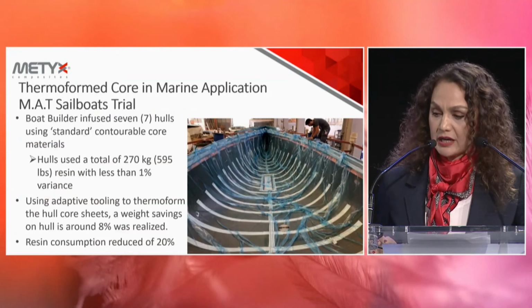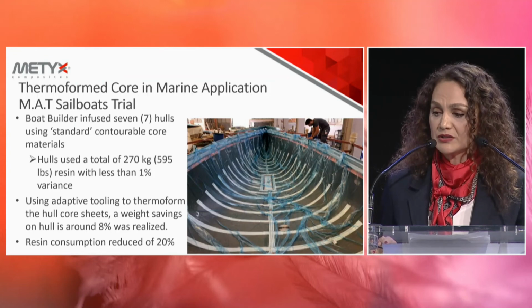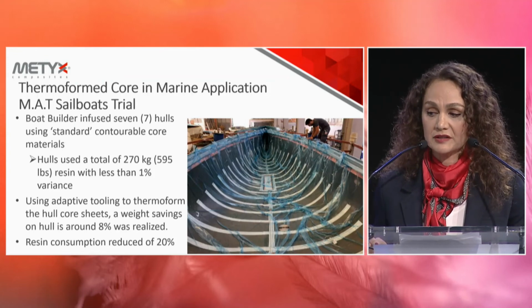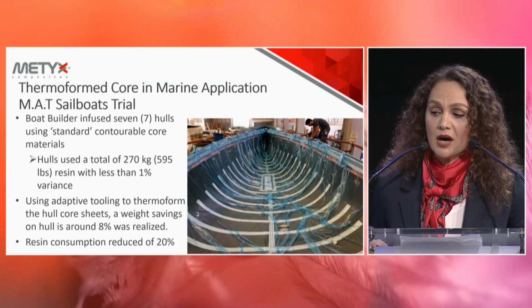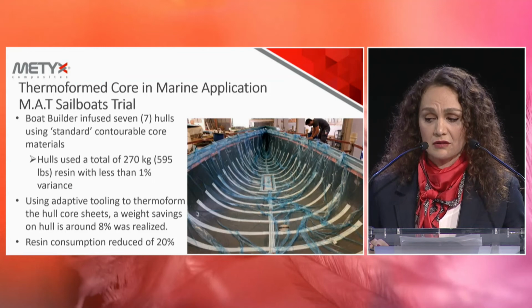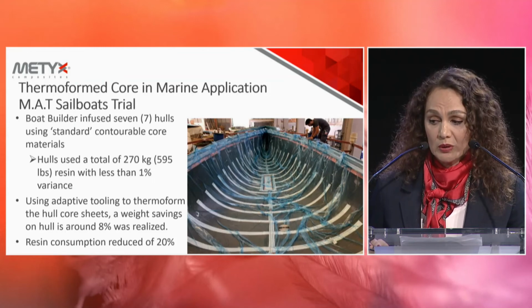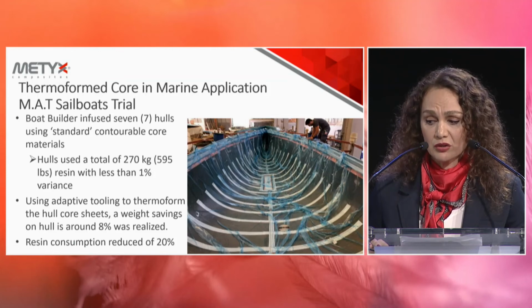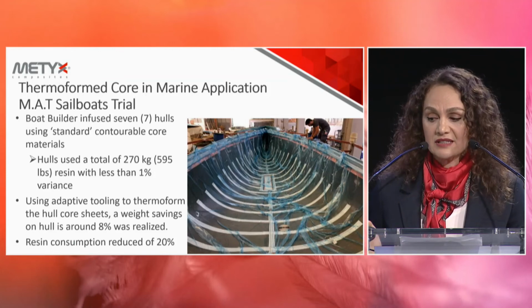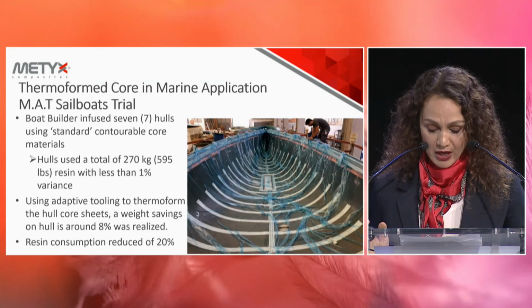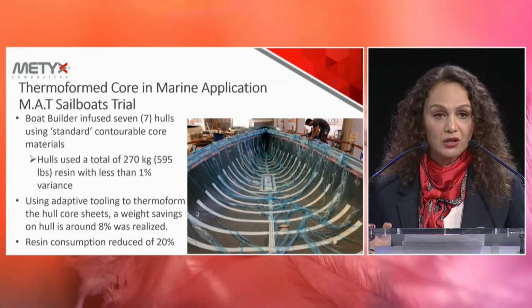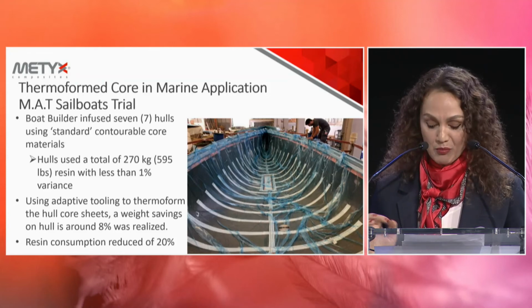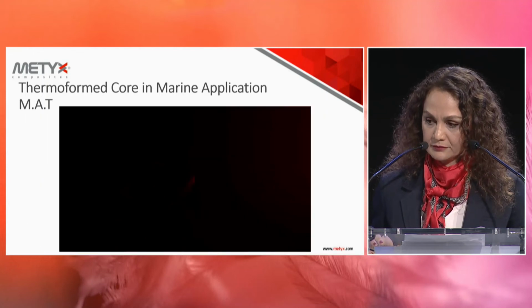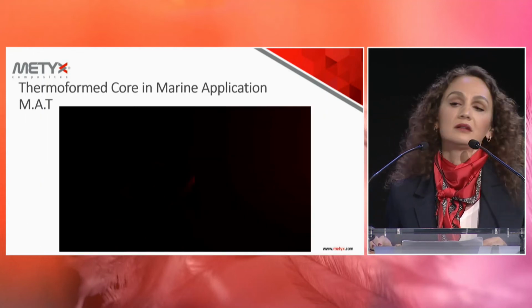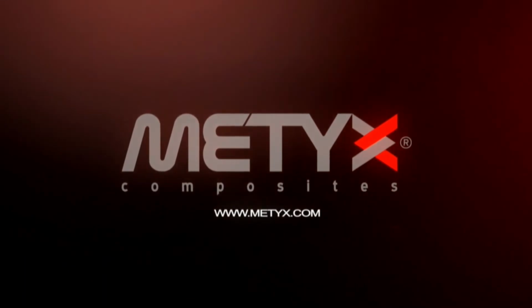This particular boat builder, MAT, produced 7 hulls using standard core materials. The hulls used a total of 270 kg resin with less than 1% variance. But using adaptive tooling to thermoform the hull core sheets, we achieved a weight savings on the hull of around 8%, and the resin consumption was reduced by 20%. That was what we were looking for in a sailboat. We are looking for the market. We have a short video here of how we use the adaptive mold and how we manufacture this hull with the thermoformed core.